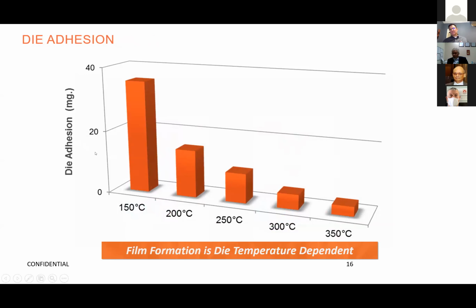Okay, die adhesion. So when we spray a die with different lubricants, we talked about Leidenfrost. At the high temperatures, if you spray a set amount of die lubricant, only so much is going to adhere to the die. Obviously, as the die temperature goes down, you get better adhesion because you're not fighting against that Leidenfrost so much, correct?